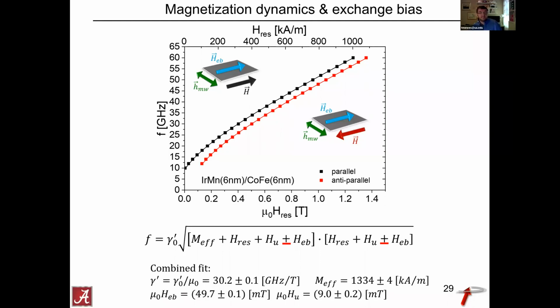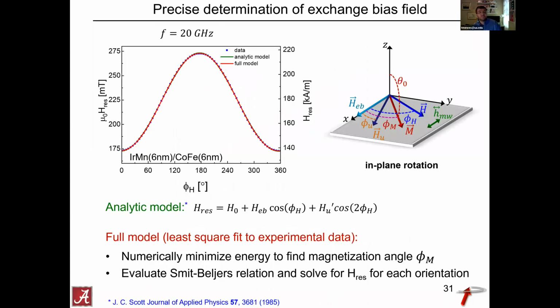But you can actually do a lot better than this, because what you've done here is you just measured along two high symmetry directions of this system. You can go ahead and do angle-dependent measurements of the resonance frequency or the resonance field in this system. And that is shown here. The points here, believe it or not, are data points measured with FMR. This system is iridium manganese and cobalt iron, a system that's commonly used in industry. And it'll become clear why that is in a little bit. What you see here is the